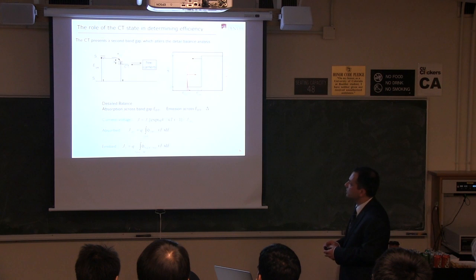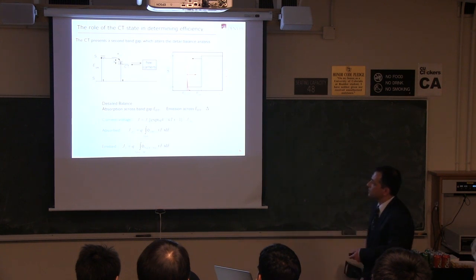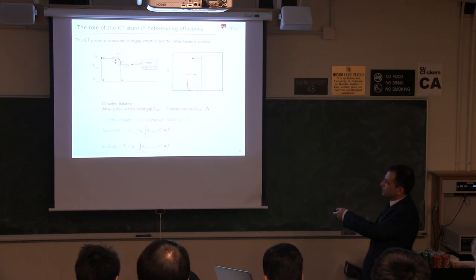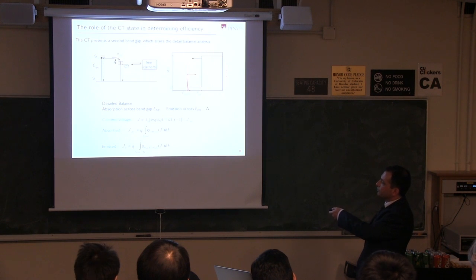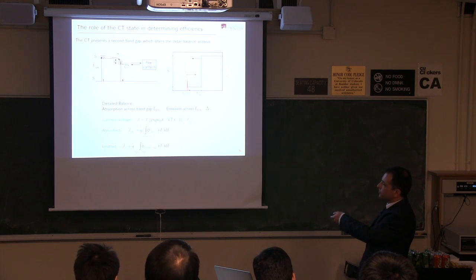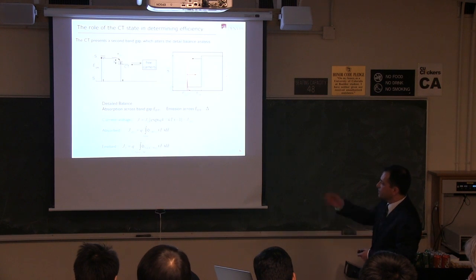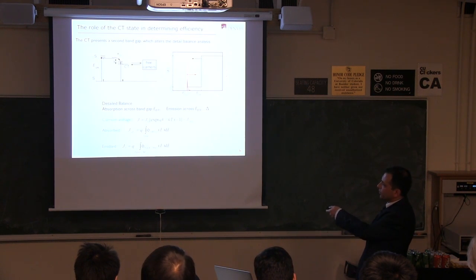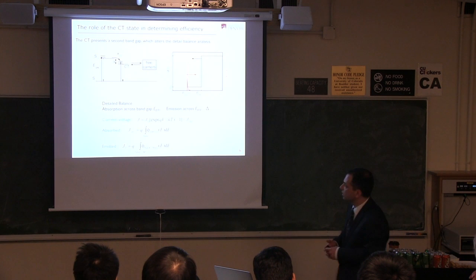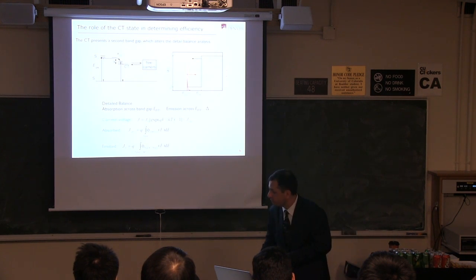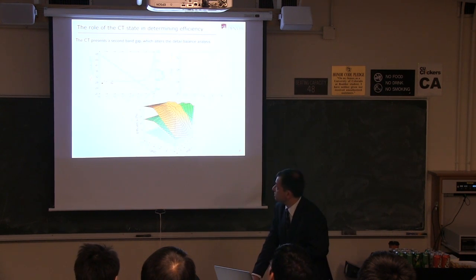But here we're saying that the emitted photons are coming from a different band gap than the absorbed photons. So what we're going to have to do is integrate the current. For the absorption, we're going to integrate from the optical band gap of the absorption. But for the emitted photons, the band gap changes from E gap to E gap minus delta. So we've changed this integral a little bit here. So that folds into the J absorption in the current voltage curve, and that changes the device JV behavior. So I'll just show you the results.